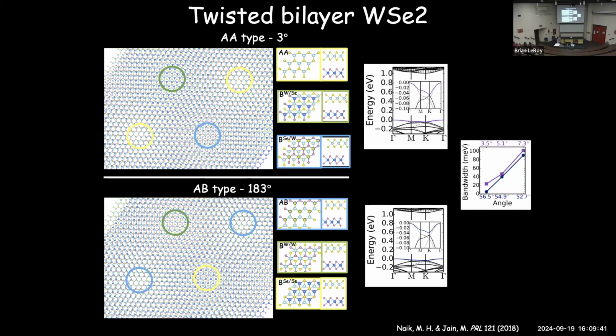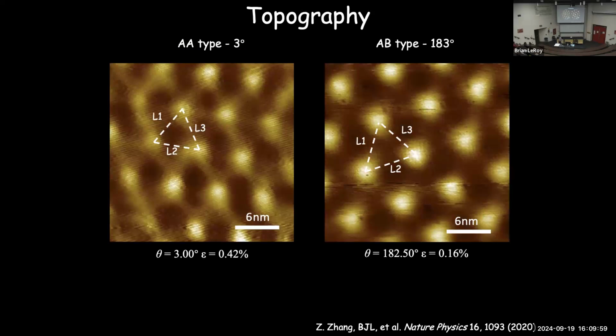And so those are the bands that we're interested in studying: what happens when you make these bands flat so that they have very little dispersion. Because at those points, you expect to have a very high density of states. And that's where you'd also expect to see correlated electron phenomena. So we made 2 samples here, one of the 3-degree type and one of the 183-degree type.